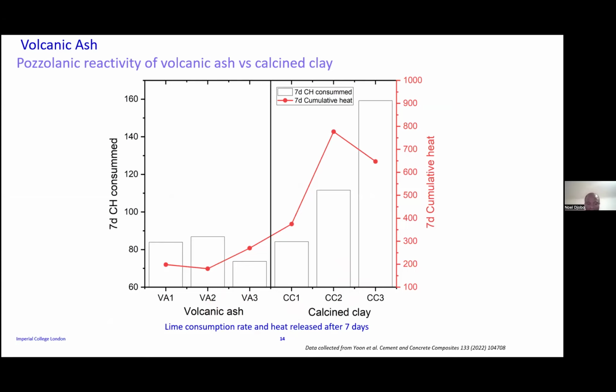So here, when you want to make your blended cement, to know that your supplementary cementitious material is a suitable material, you need to make a test which is called calcium hydroxide consumption or lime consumption. Because when you mix the supplementary cementitious materials with Portland cement, and when you add water in the system, that SCM will react with cement and it will make cement to be stronger and more durable. But here when we compare the reactivity of the volcanic ash and calcined clay, it's clear that volcanic ash is very less reactive than calcined clay.